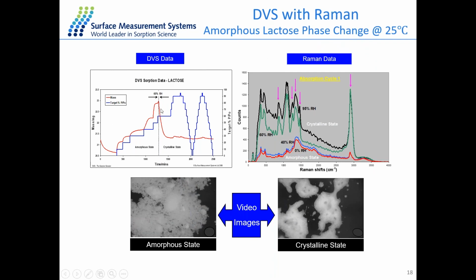So on the left-hand side is the DVS data, where you can see the red line for the change of mass for the sample, and it is the amorphous lactose material at 25 degrees. So at the previous humidity steps, the sample is picking up the moisture, and exactly at 60% RH here, there is a significant drop in the mass. And this is due to the amorphous to crystalline phase change, because the crystalline material has smaller surface area as well as less sorption capacity.